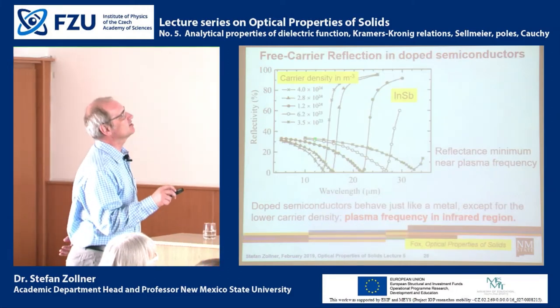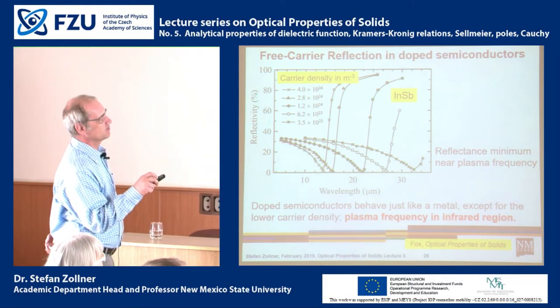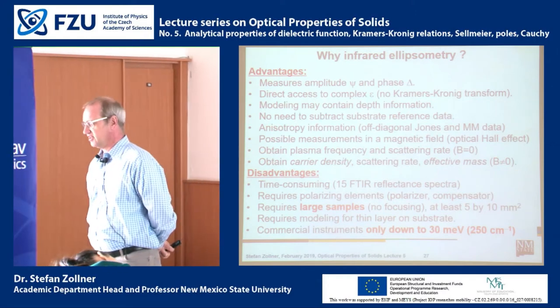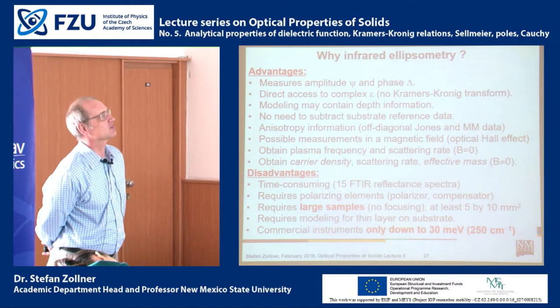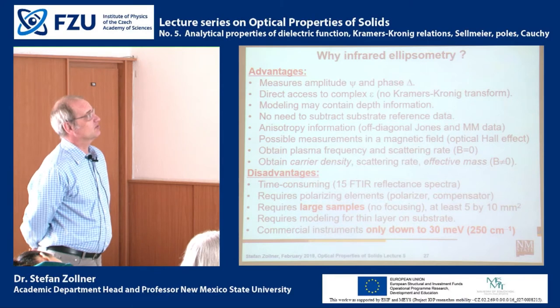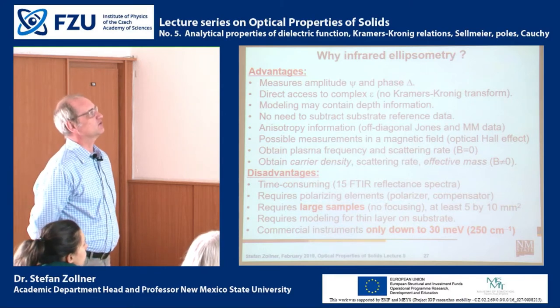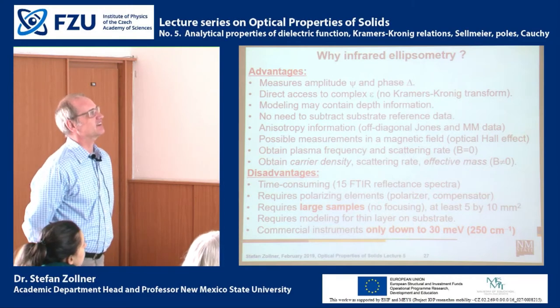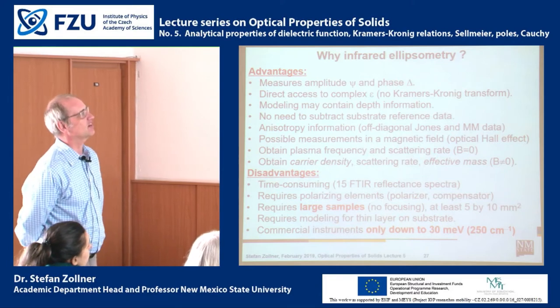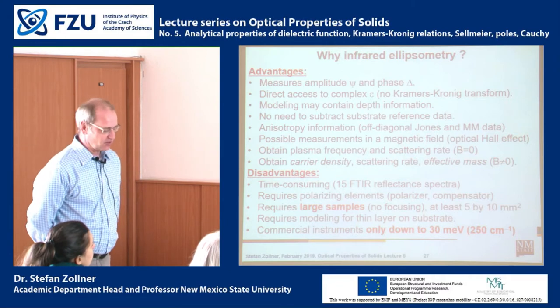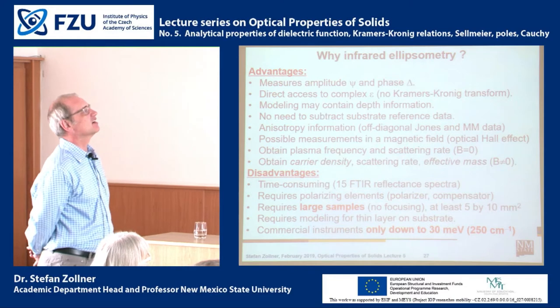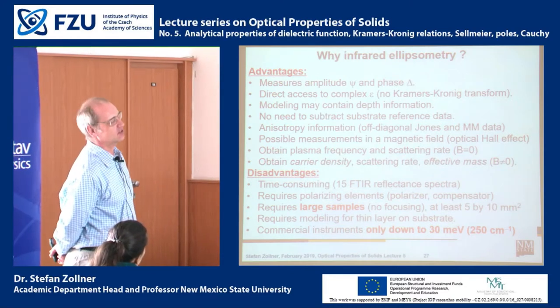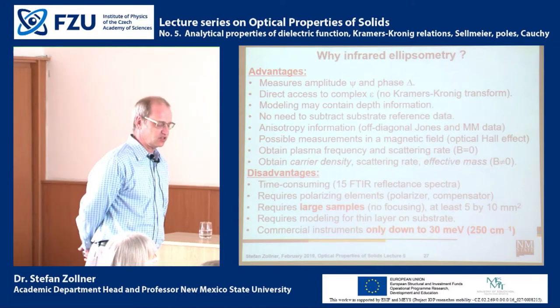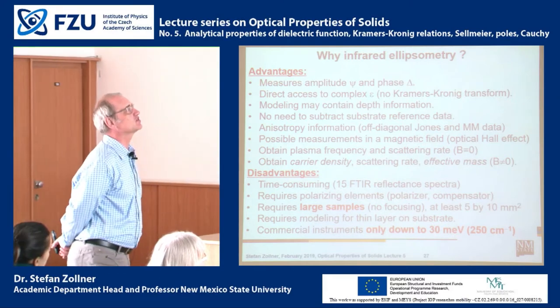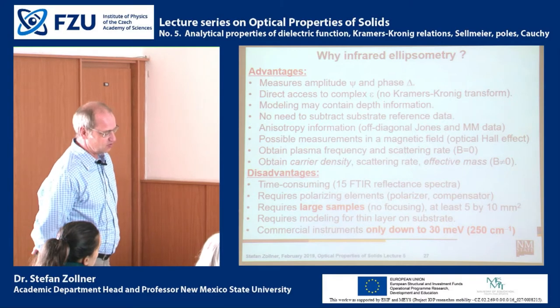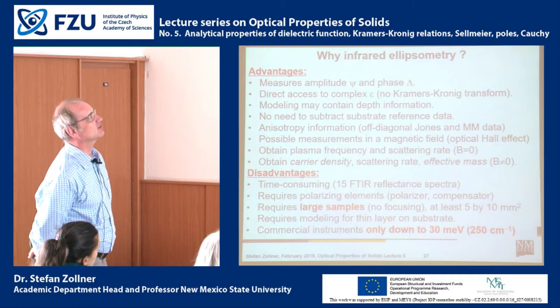So these data here are reflectivity. But why do people nowadays measure infrared ellipsometry rather than infrared reflectance? If we do ellipsometry, then we measure two quantities, both an amplitude and a phase, and therefore we have direct access to the complex dielectric function without the need for a Kramers-Kronig transform. And therefore, it is easier, at least for me, to interpret the dielectric function. It is easier for me to find features in the spectra. And I have measured some crystals where I believe that we have been able to get more accurate results with our ellipsometry measurements than with the reflectance results that were in the literature.